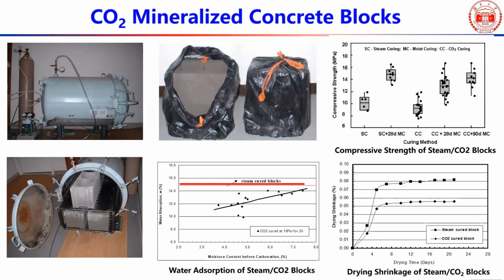This is actually after 24 hours of steam curing, and then further moisture curing up to 28 and 90 days. We can see the strength of the block continue to increase significantly, because as I mentioned earlier, the carbonation degree of cement inside the block was only about 25%. Now we can reach 50%. Okay? So still 50% cement uncarbonated inside the block continues to hydrate and so continues to enhance the properties of the blocks.